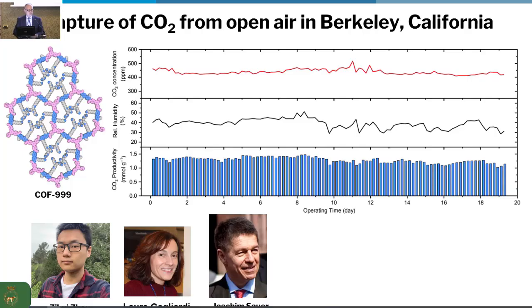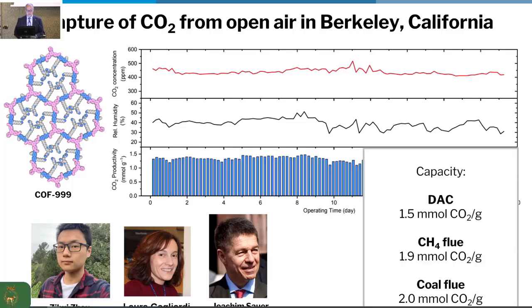Well, it takes up CO2 and there's absolutely no CO2 left in the air once it goes through. And you see that it takes up CO2 very nicely, and the CO2 uptake scales with the humidity. The more humidity is in the air, the better is the uptake. But if you take one humidity level, let's say 37%, it will look absolutely reproducible. So this variation corresponds to the humidity rather than the stability of the material. This material can cycle. In this report, we cycled 100 times with absolutely no imprint left on the material. This is the kind of stability you need to have a viable material for CO2 capture from air.